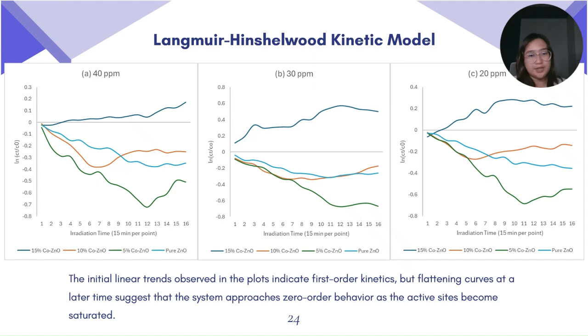Supporting the use of this analysis, the Langmuir-Hinshelwood model of the experiment is shown in this figure. A plot of ln(Ct/C0) by irradiation time at T1 to T16, where data points have a 15-minute interval each. In this figure, the general trend is that 5% doping indicates enhanced degradation rates compared to pure zinc oxide and other cobalt doping concentrations. This suggests that although cobalt doping can improve photocatalytic activity, there is a threshold wherein cobalt doping may be too much and it could decrease the photocatalytic activity under visible light.